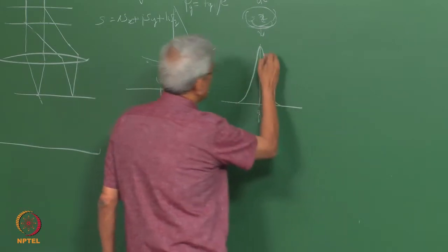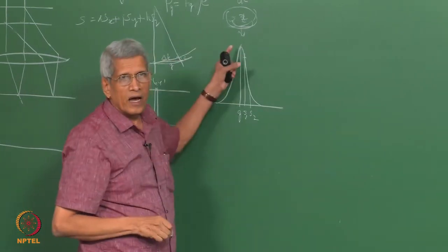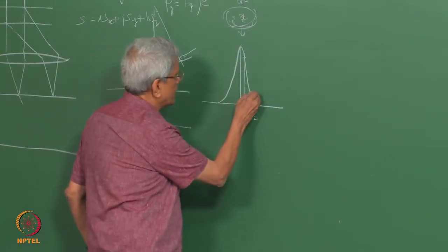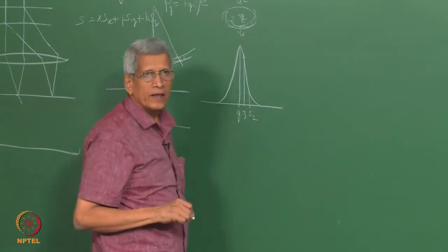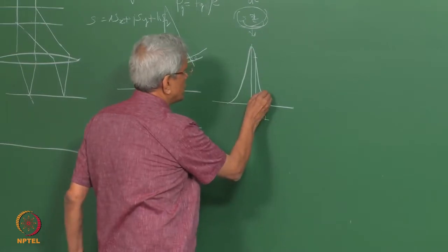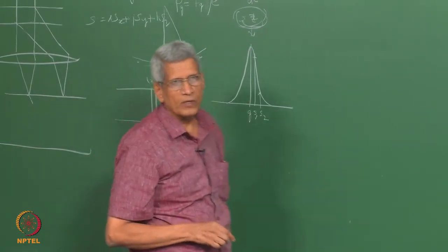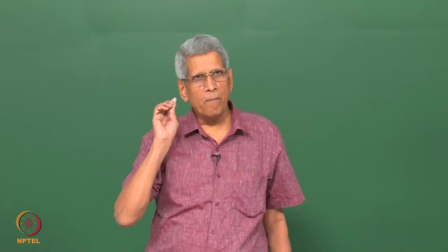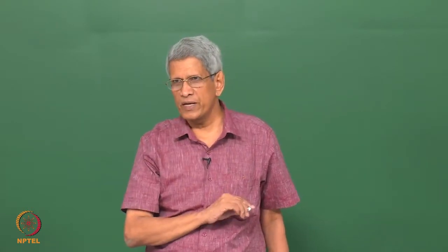S1 is close to the Bragg condition, so the intensity or the amplitude of the scattered wave is going to be very large here, whereas compared to the intensity which you should have at exact Bragg orientation, the intensity is going to be very small for this value. That means this corresponds to a condition where the amplitude of the scattered wave is much smaller compared to that of the incident wave, right? So the kinematical theory is valid in this case.